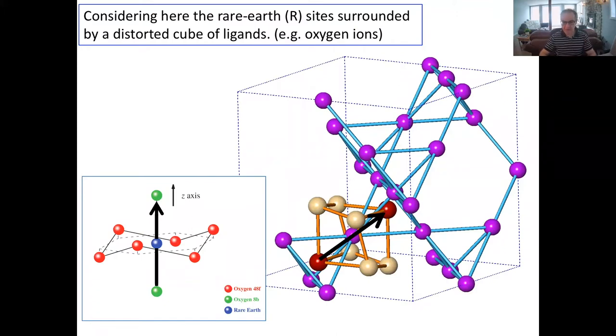in these systems, the rare earth ions sit on a lattice of corner-sharing tetrahedra, a portion of which is illustrated here. An important aspect of the physics of these materials is the fact that around each rare earth ion, there is a distorted cube of oxygen with two different sites occupied by these oxygens. One of the oxygens, marked in dark red here, occupies the geometrical center of each tetrahedron. And there are six oxygens that form a puckered hexagon perpendicular to this direction, which are marked by the six beige oxygens here. So the oxygen environment around each rare earth looks like a cube of oxygen that is being distorted while keeping the volume of that cube constant.